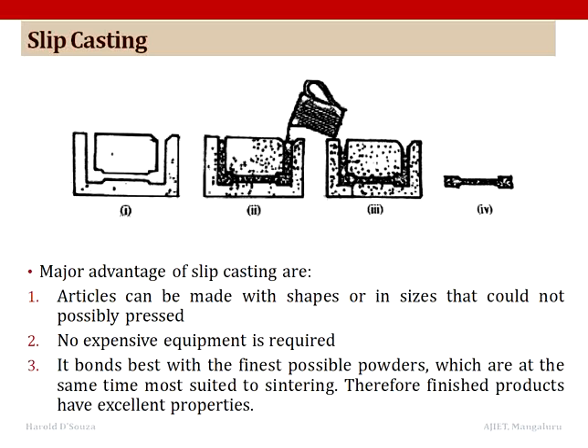A slip is a suspension of a metal or a ceramic powder which is finer than 5 micrometer in water or with other liquid, which is poured into an absorbent mold, usually plaster of Paris, dried and subsequently sintered. Slips are usually made up of the constituent powders, a dispersing agent to stabilize the powder against colloidal forces, a solvent to control the slip viscosity and facilitate casting, a binder for giving green strength to the cast shape and plasticizers to modify the properties of the binder.